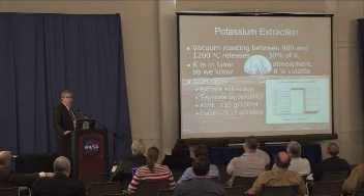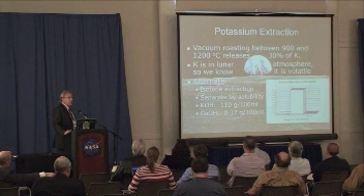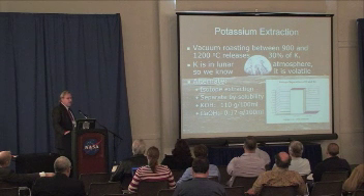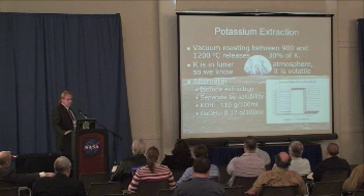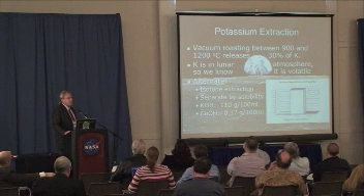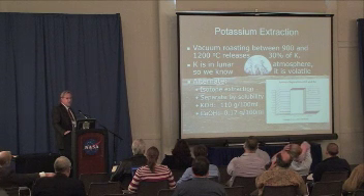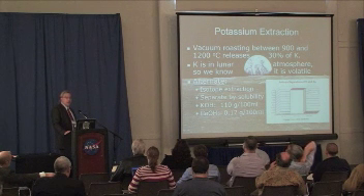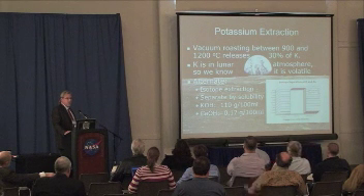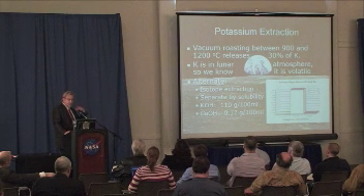To get potassium, there's not a whole lot of potassium on the moon, but there are places where there are more deposits. One way to get this out is through vacuum roasting. If you roast it between 900 and 1200 degrees C, you can get up to 30% of that potassium out. To verify this, we also looked at studies of the lunar atmosphere and found that there is some potassium in the lunar atmosphere, rare as it is, which shows that even sunlight hitting the surface of the moon can cause some of that potassium to come right out.